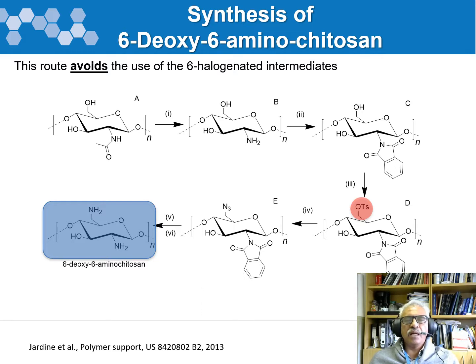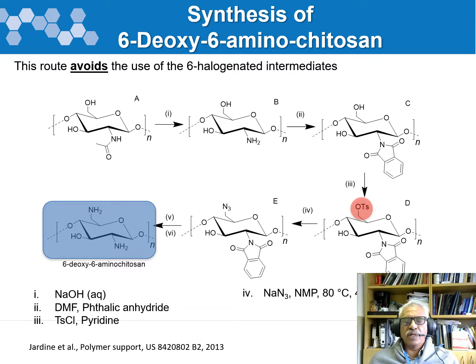So we changed the process slightly. First of all, we still need to do a deacetylation, and then of course take the deacetylated chitosan and protect it as the phthaloyl. Then, instead of converting this to the halogen, we found it was better to use tosyl chloride to produce the tosyl, which is then substituted with the azide, and then reduced using the Staudinger reduction to the amine. And then, of course, the final step is to remove the phthaloyl group to give us the 6-deoxy 6-amino chitosan. We got a much better product. However, it's still not scalable because it still contained quite a bit of triphenylphosphine, and it's not as soluble as we would have liked.